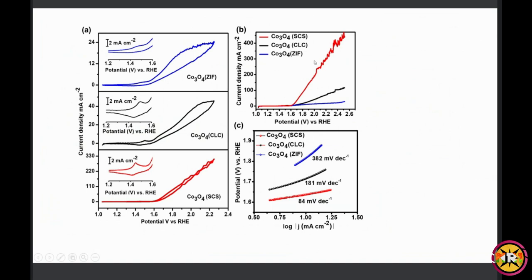Now I have done LSV, and here I saw the overpotential for Co3O4 SCS is only 400 millivolt, that is quite less than the others. Basically, overpotential we are calculating from the standard of 1.23. I have observed the overpotential is quite less and current density is quite higher than the other two. And now coming to the figure C, this is the Tafel law.